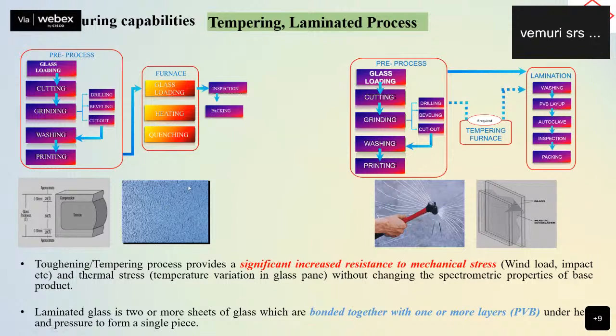As you see here, these are the processes that the coated glass will follow. Once the coating has been developed by large area sputtering, the glass loading will be there, cutting will be there, grinding will be there. After that, drilling with respect to the specific shape, then glass loading into the heating and quenching. Then inspection should happen, where industrial norms will be followed with respect to ISO, EN and NFRC standards. Similarly, these are the different processes for lamination as well as tempering.